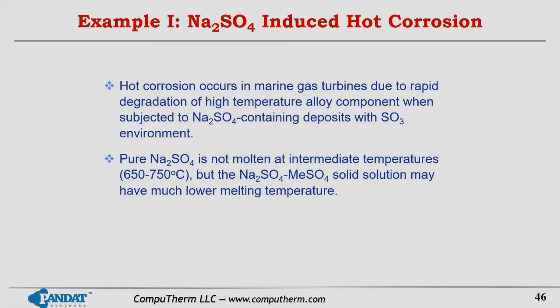The first example is sodium sulfate induced hot corrosion. As we know, hot corrosion occurs in marine gas turbine engines due to rapid degradation of high temperature alloy components when exposed to sodium sulfate containing deposits and also SO3 gas environment.